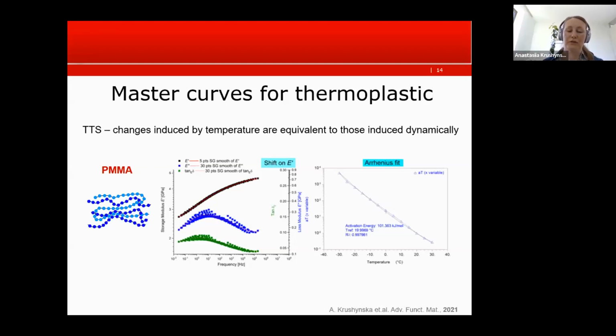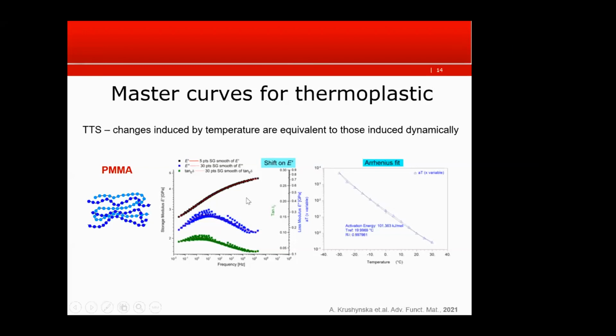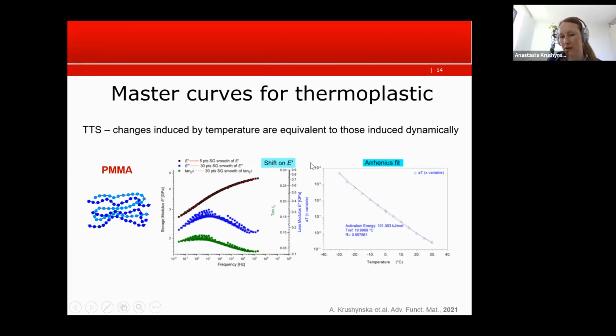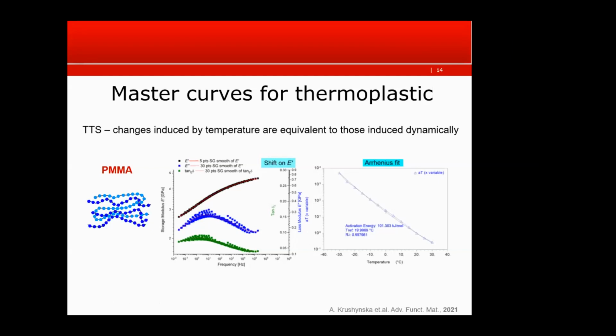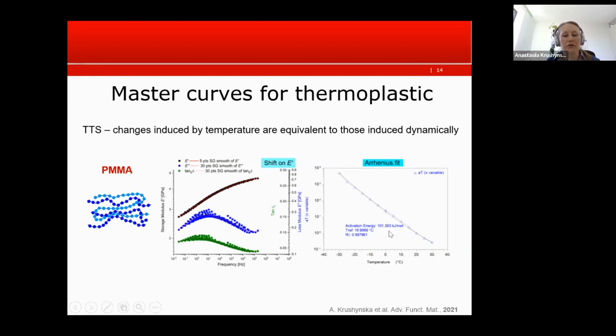Okay. Yes. So first of all, before doing the shift, we read the literature related to this material, PMMA and epoxy, and identified the most possible fits that were working nicely for other researchers. Then we had our measurement data, and if I remember correctly, because it was not me who did these measurements but my Italian colleagues, they used the program which is a part of the rheological instrument for these measurements. But after they obtained a more or less good visual shift, but not only visual, they also estimated the quality of the shift by calculating some coefficients, and they calculated the activation energy.